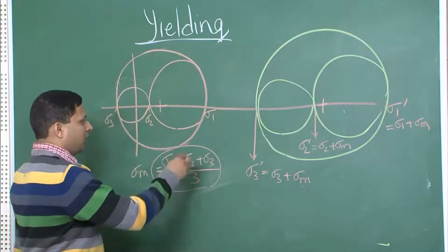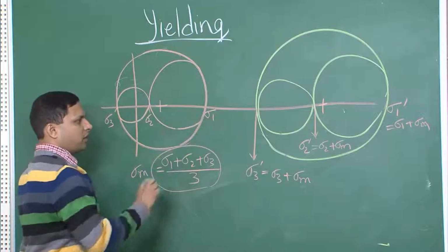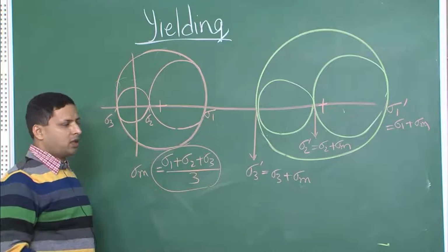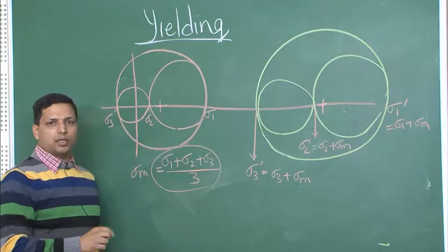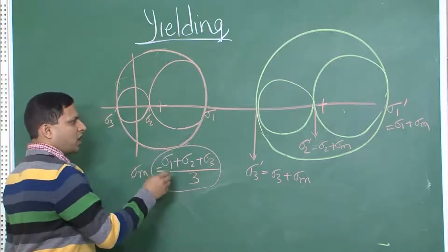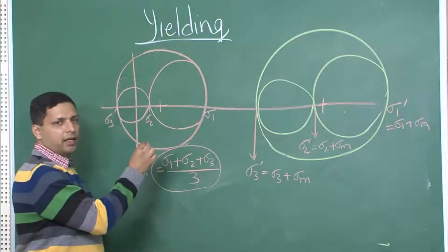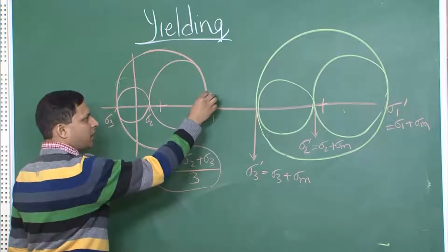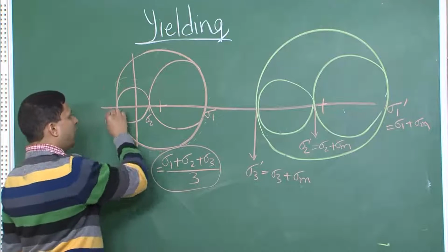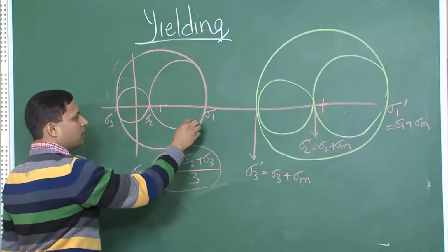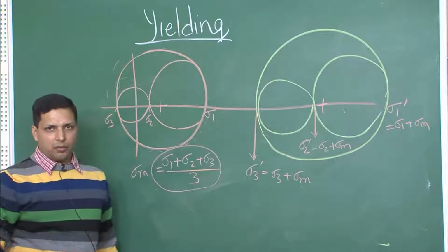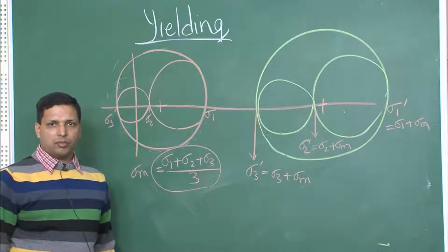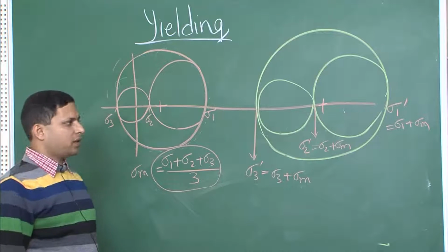And therefore, if you are actually changing something which is causing the size of the diameter of the circle to change, that is the only thing that can actually change the state of yielding. So, let us say we start with a very small circle, there yielding is not taking place, keep increasing it, and there may be some critical size at which yielding takes place. As soon as the circle size reaches this value, the material starts to deform plastically, and anything beyond that the material has yielded.